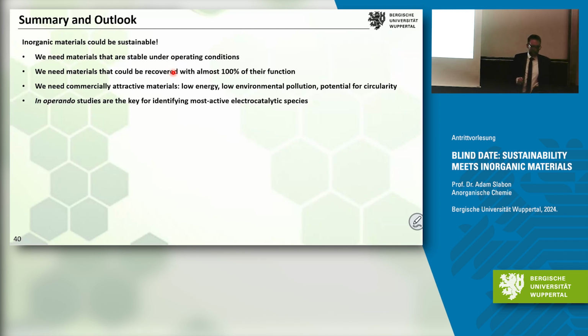We need a potential for recovery of the materials with 100%, or almost 100%, function, because you have to work in a circular pathway. And we need the scale-up to go from invention to innovation - commercially attractive materials, low energy, low pollution, and this potential for circularity, like you've seen with the batteries. For catalysis, I believe very much in operando studies to identify the most active catalytic sites, and then in the next step you can think about how to stabilize them chemically.